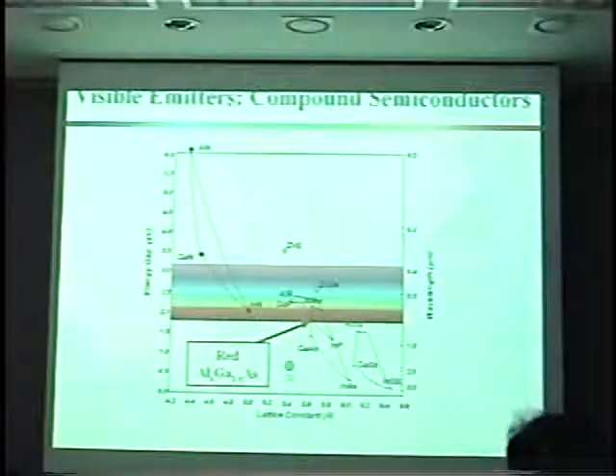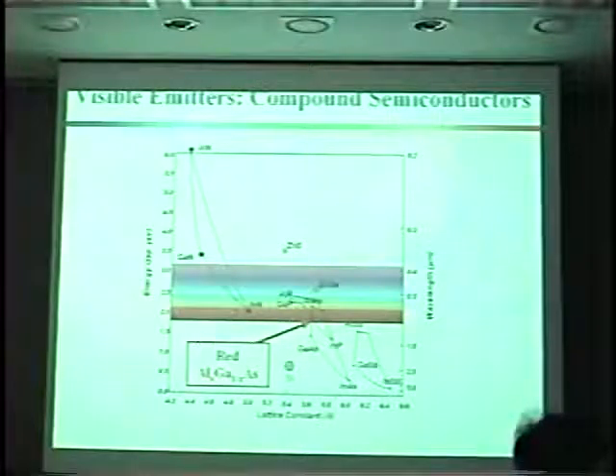I'm sure most people have seen this plot of band gap versus lattice constant. The reason these are two important physical parameters is that the energy gap is characteristic of the light emission wavelength, and the lattice constant is required because lattice mismatch often deteriorates the material quality, and generally the devices we're trying to make are heterostructure devices, and if possible we like to do the lattice matching. So often we're doing band gap engineering, where we're engineering the band gap to select a particular wavelength of emission. At the same time, we're trying to match lattice parameters between active layers and confining layers to be able to get a higher quality device.